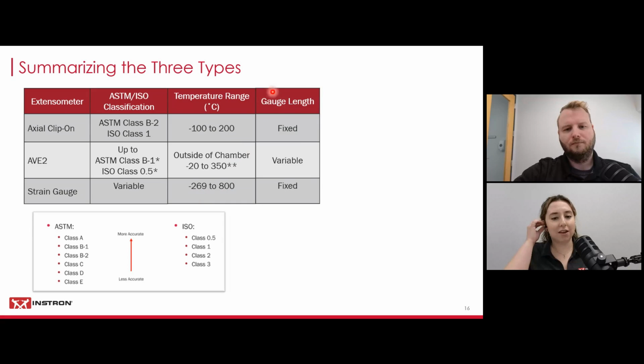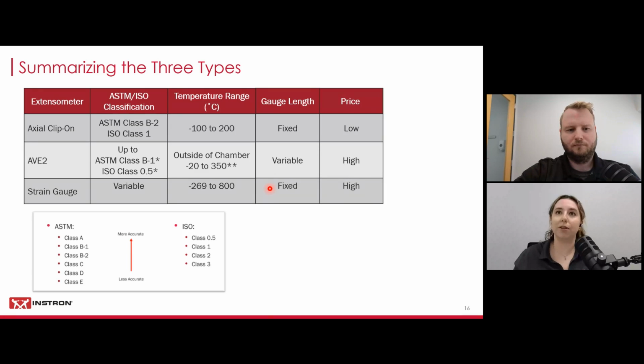Your gauge length for your axial clip-ons, that's going to be fixed. So if you have varying gauge lengths, 10 millimeters, 20 millimeters, 50 millimeters, you have to purchase a clip-on for each one of those gauge lengths. Your AVE2 is variable as it is able to read the gauge length markings on the specimen for you. And then your bonded strain gauges are also going to be fixed gauge lengths, 3 millimeters, 6 millimeters, and you're going to have to purchase ones for the different gauges you want to test with.